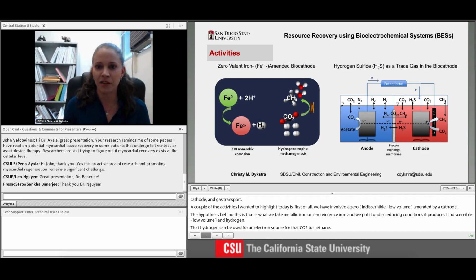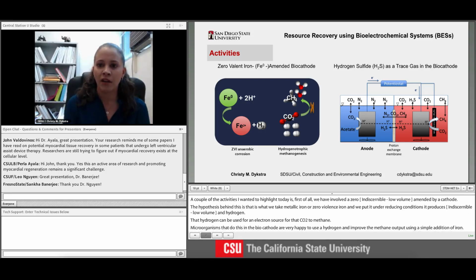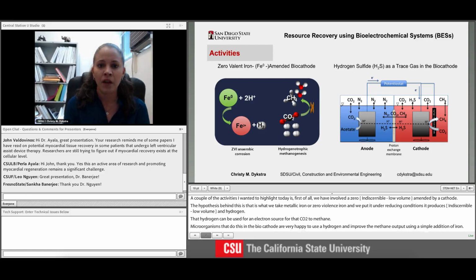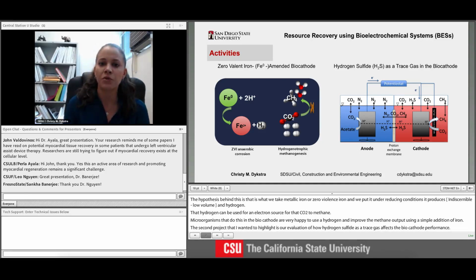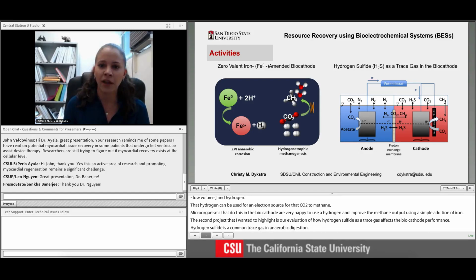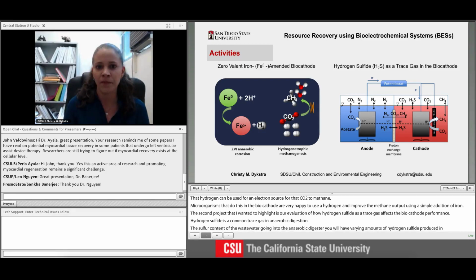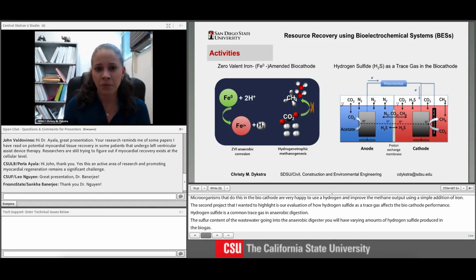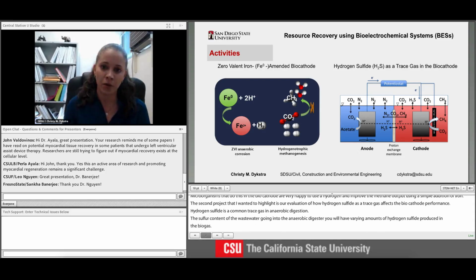The second project that I wanted to highlight is our evaluation of how hydrogen sulfide as a trace gas affects the biocathode performance. Hydrogen sulfide is a common trace gas in anaerobic digestion, and depending on the sulfur content of the wastewater going into the anaerobic digester, you will have varying amounts of hydrogen sulfide produced in the biogas. It's a toxic, corrosive gas, it's undesirable, it causes odor problems, and has to be removed prior to combustion of biogas. It's also often toxic to microorganisms, so we wanted to look at how that hydrogen sulfide in that biogas would affect the biocathode performance.